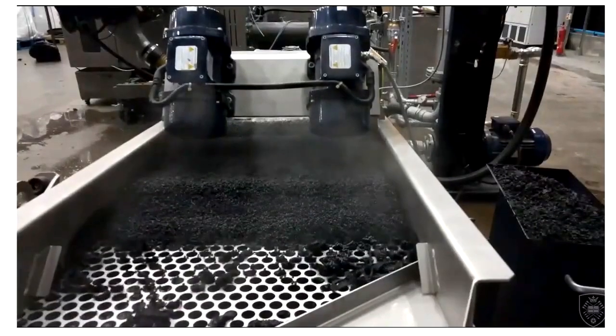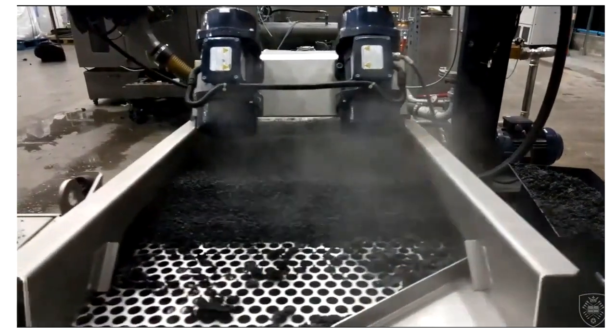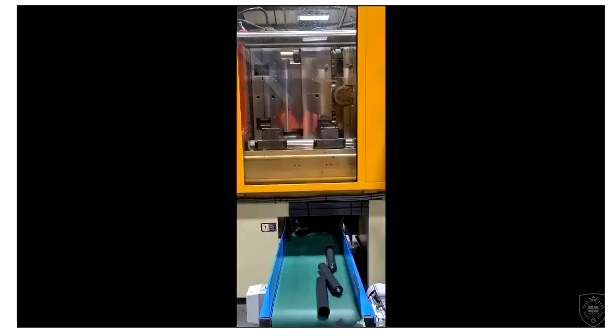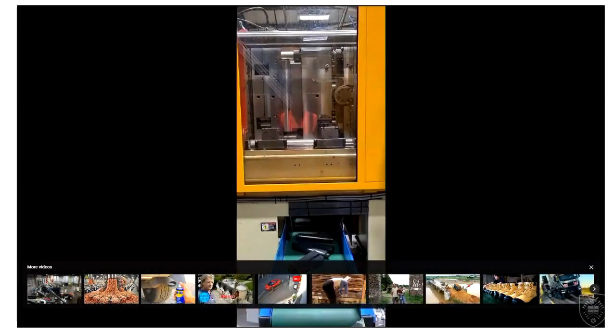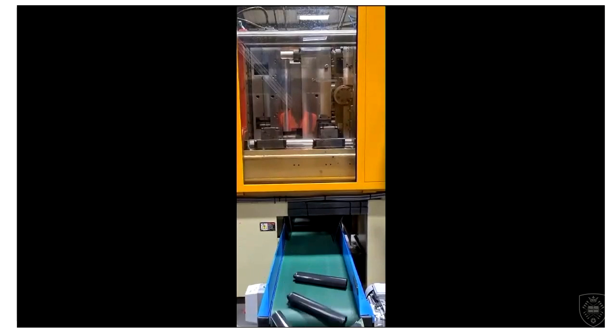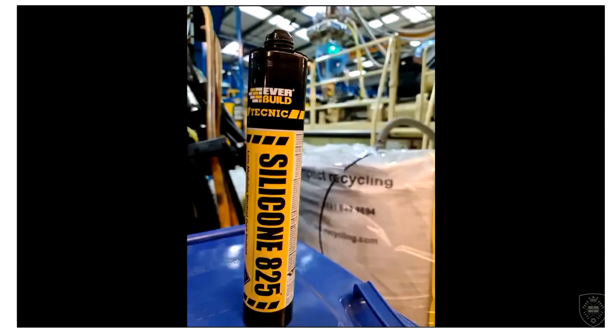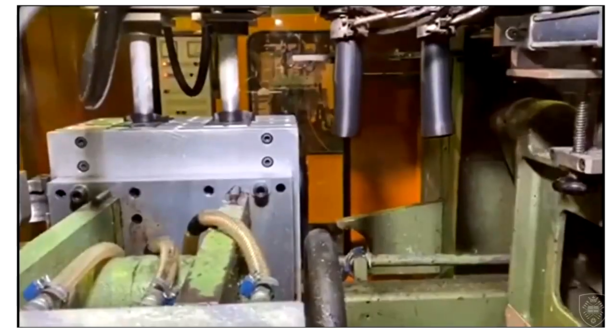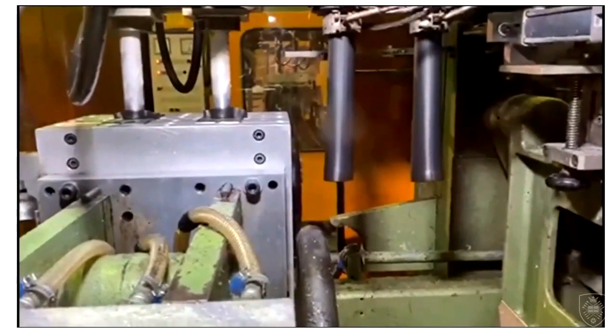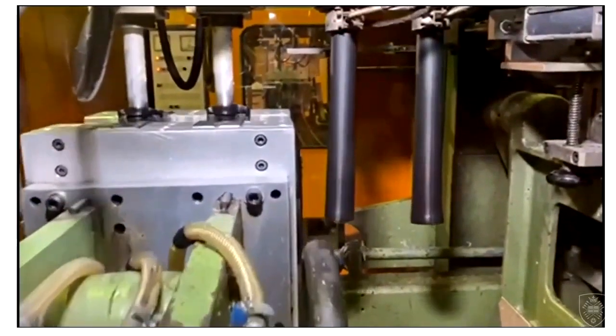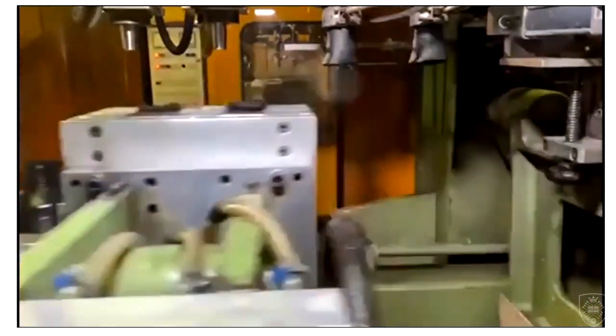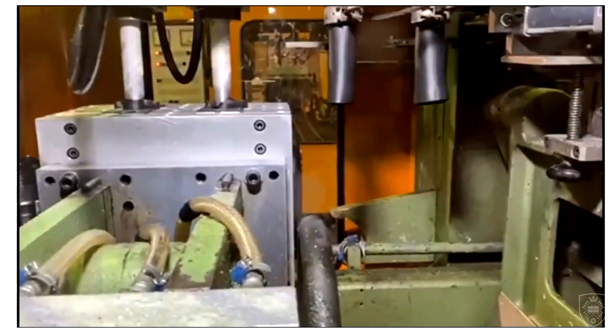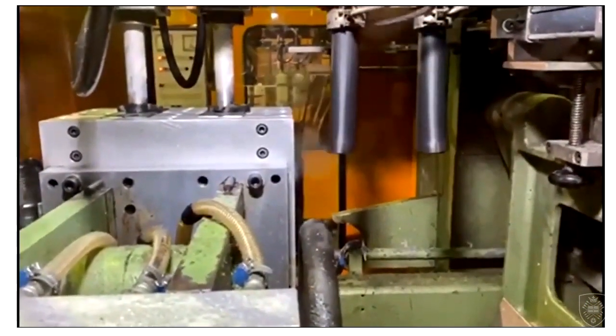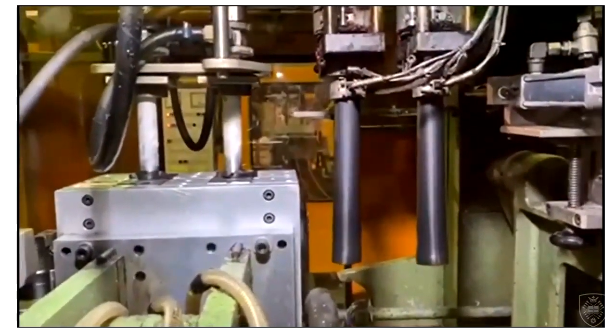The solution to the melt flow rate problem allows us to make a pellet now by using an additive. It's a monomer additive, so it's a food grade approved additive. And it means we can now make, for example, these sealant gun cartridges, which have a melt flow rate of 7. And it'll take the color as well. From the same material, we can also make these shampoo bottles that you can see here. It's a blow molding process, and this requires a melt flow rate of 0.5. So it's a patented additive. It's a big breakthrough. It's little talked about in the industry, as I say.